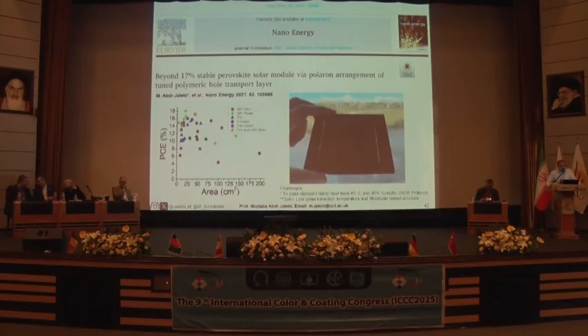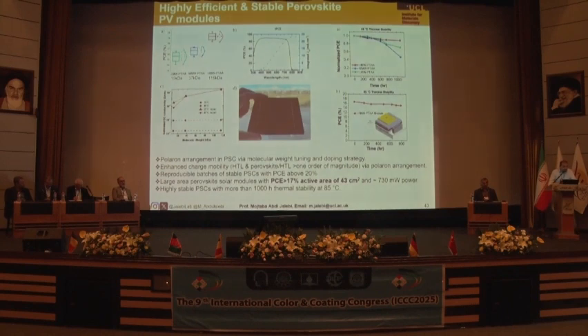One of the origins of instability is mostly coming from the layer, the so-called hole transport layer that we are using in these devices. And in this work, we focus on how we can replace that material and utilize a polymer material that can survive at high temperature. Here, for example, we use PTAA material, and that helps us make it stable. You can see the stability, the performance over time. That's a measure of the stability of our solar cell. And it also works at a larger scale. This is a module size device, over 17% for 43 centimeter squared.